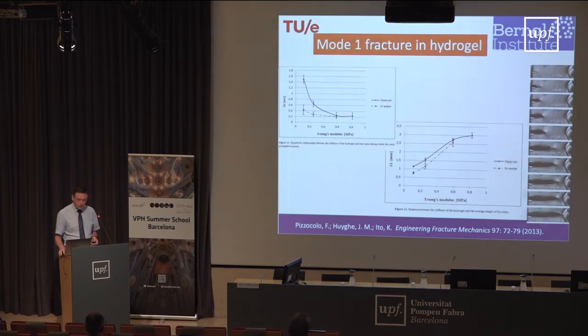And so we could also show that the distance between the teeth depends on the Young's modulus. We did many of these experiments, and you see that as Young's modulus increases, you get a longer distance that it propagates each time between the steps. And the time it pauses does the opposite. It is higher for low Young's modulus and lower for high Young's modulus.